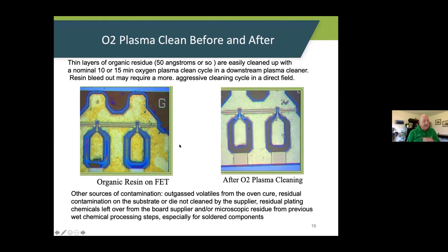So here's kind of a picture left and right. This is kind of the before and after shot here. But a conventional plasma treatment, you know, maybe 10, 15 minutes in a chamber, maybe only 5 minutes of actual cleaning. You should be able to easily clean up 50 angstroms, maybe more, of organic contaminants.